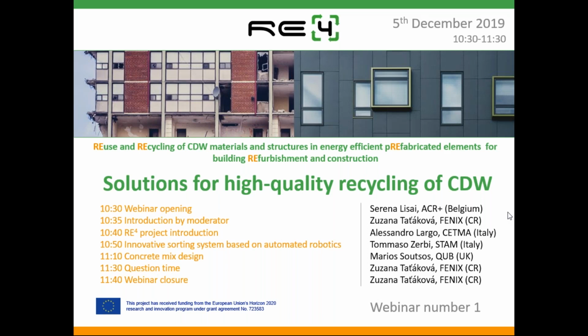Recycled aggregate, as I said, tends to be a mixture of aggregate, old concrete, and masonry, red brick basically. The density of these aggregates is lower than newly quarried aggregates, and by using them there is a detrimental effect on the strength, and therefore, as I included in the presentation, there were different approaches to maintaining the strength required by the factories, by either increasing the cement content and reducing the water-cement ratio, or in the case of the building blocks, by increasing the density of the building blocks and reducing the air in the building blocks. I hope that has answered the question.